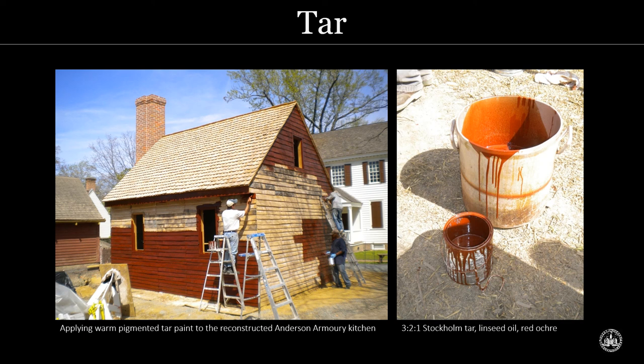Just over 10 years ago, we reconstructed the site of an 18th century armory and tinsmith shop. And these utilitarian buildings were coated with pigmented tar. The recipe that we used was a 3:2:1 ratio of Stockholm tar, linseed oil, and red ochre pigment. And the tar was warm when it was applied, and I can see why it was used as a preservative, because it really soaked into the pores of the wood, particularly because these weatherboards were riven, not planed, so they were rough, and they took up the tar more readily.